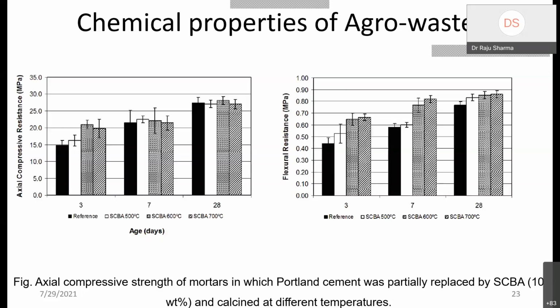Okay. And if you see the flexural resistance, in a similar way as the left image, on the right side the flexural resistance of the product is increased with 28 days curing at 10% SCBA replacement of cement. Of course, at 600 degrees Celsius it gives the good result. So in an optimum way, because in your research you cannot say directly, when you have a lot of variables, you have to find an optimum statement to justify your results, right? So here we can say that 600 degrees Celsius is good at 28 days with replacement of cement at 10%.